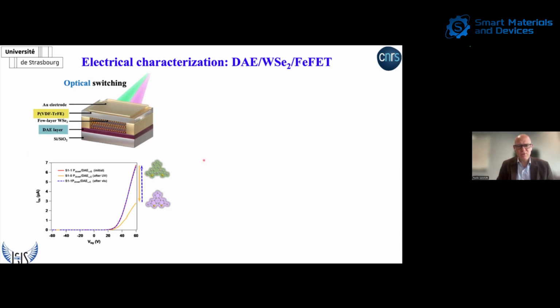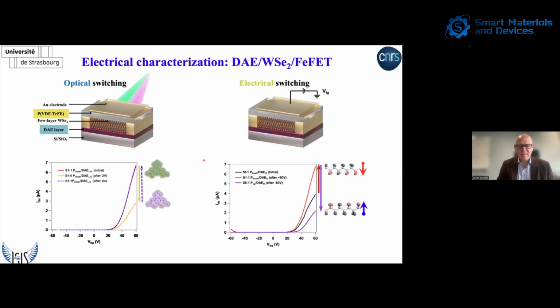Now, we had to learn how to use the ferroelectric material. And actually, we noticed that upon applying plus 60 volt, we are orienting all the dipoles pointing towards the surface of the tungsten diselenide. This is the highest current possible. And then upon applying minus 60 volt, we swap the dipole orientation, they're all pointing up. And this we have a change of 68% of the current through a junction, which is also totally reversible. So these are two types of, let's say, stimuli that are non-volatile.